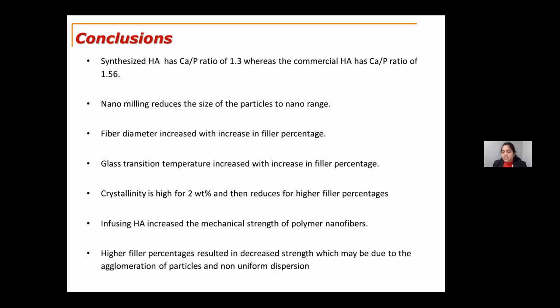From the DSC results, we understood that the glass transition temperature has increased for fibers infused with the hydroxyapatite particles. However, the crystallinity for the fibers with 3-weight% has reduced compared to the 2-weight% and 1-weight%. And infusing the hydroxyapatite nanoparticles into the polycaprolactone solution has definitely increased the mechanical strength in terms of the tensile strength, Young's modulus, storage modulus, and the loss modulus. So overall, infusing the hydroxyapatite nanoparticles has shown better results for thermal and mechanical properties compared to the neat fibers.